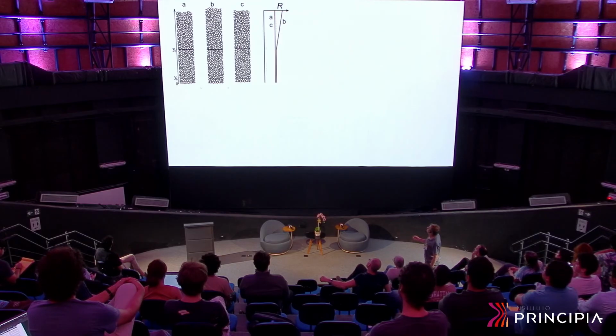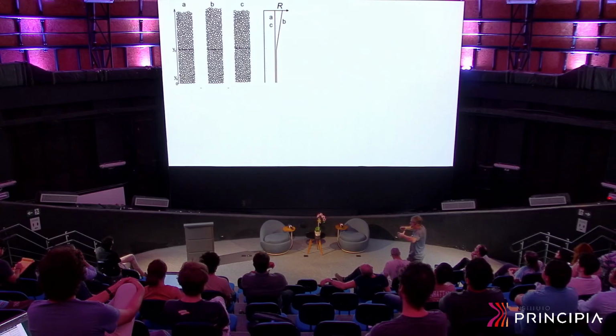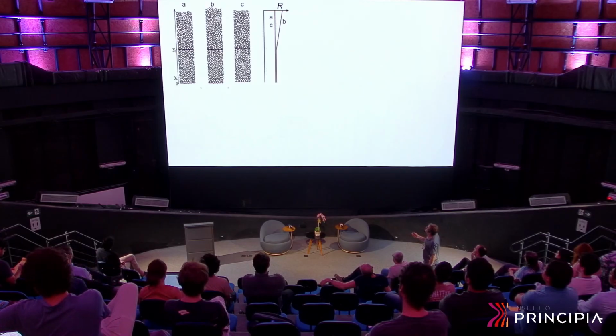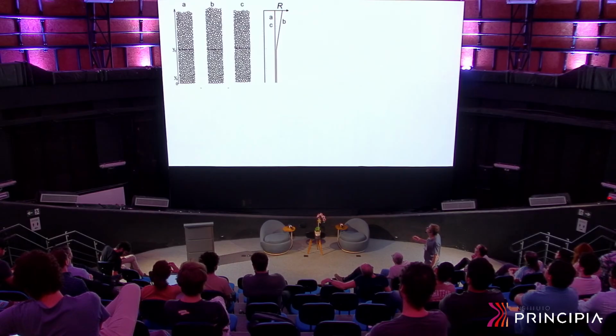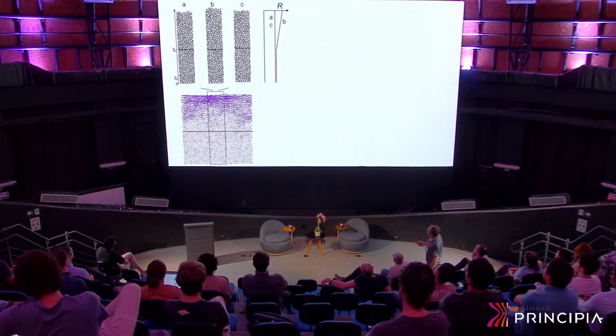So when we increase the radius of the particles, the system swells, becomes larger. This is evident here from the increase in the surface, the vertical surface here, and then we go back to the original configuration. The question is, is this configuration the same as this one here? The answer is presumably, because of all I said, presumably not. And the fact is that, in fact, it's not.